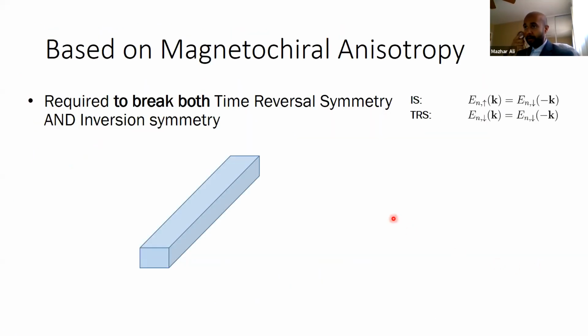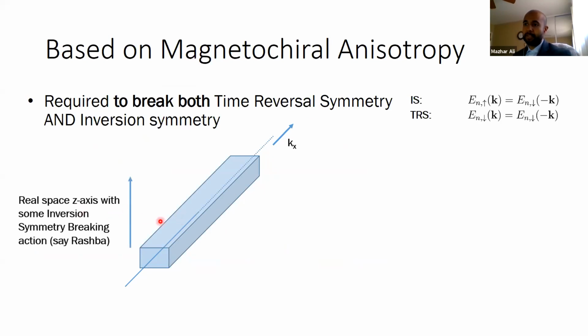So what is Magnetochiral Anisotropy? Basically, let's imagine a material, so this cube or whatever, that breaks both time reversal and inversion symmetry. The usual relations are up here. I'm going to play a little fast and loose with my directions, so just bear with me, but if we imagine kx along this direction, and we imagine that there was in this material some real space inversion symmetry breaking action. So for purposes of this, let's say Rashba spin orbit interaction. Let's say it was along the z-axis, and then you would apply a magnetic field to break time reversal symmetry.